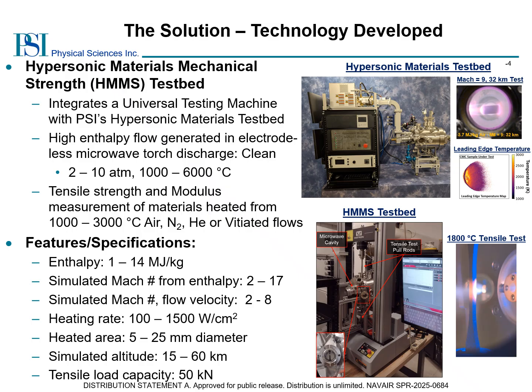Testbed specifications include an operating enthalpy range between 1 and 14 megajoules per kilogram, simulated Mach numbers up to 17 based on enthalpy and up to 8 based upon the velocity of the jet, heating rates up to 1500 watts per centimeter squared, heated areas up to 25 millimeters in diameter, dependent on the simulated altitude, which ranges from between 15 and 60 kilometers. The current load frame has a maximum tensile load capacity of 50 kilonewtons.